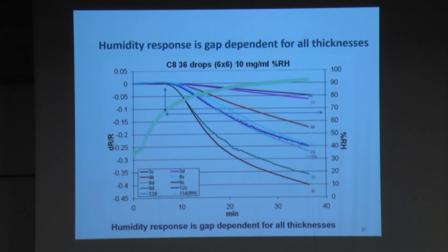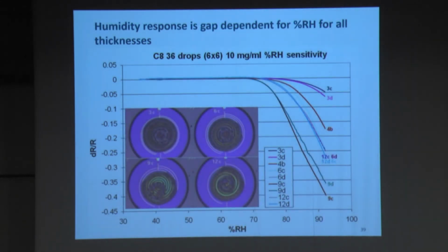However, when we expose it to water in a very slow way, we increase the concentration, the humidity, from about 30% to about 90%. What happens is there's a huge gap effect of the electrodes. And it starts at about 60% of relative humidity. Okay, I'll show you later. This actually looks like this. You see, from 60% up, there's a big difference of the response at high humidities.